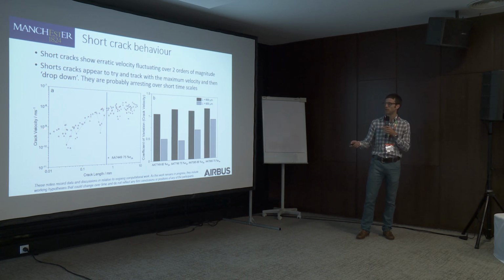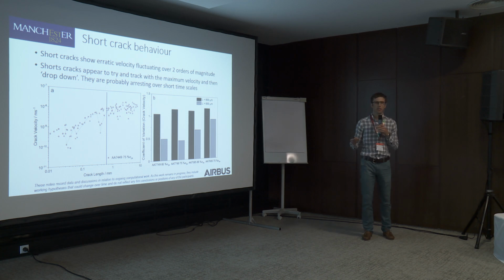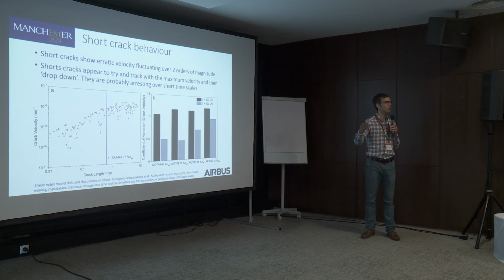the crack arrest markings. But it's interesting that this velocity tries to track at the highest rate for any of these cracks, but then drops down, suggesting that it cracks as fast as it can, but then meets an obstacle and drops out. And this threshold that we've put in here is about 600 microns, where we see that transition in behavior, and that corresponds almost perfectly to the average grain dimension in the longitudinal direction, which is the direction that these cracks are propagating in.